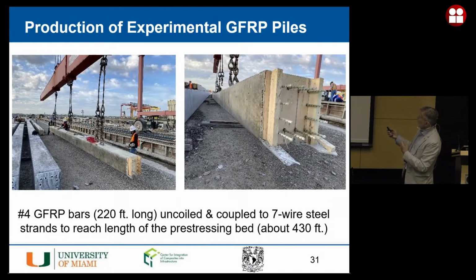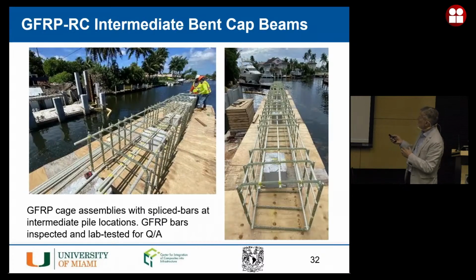So these are the piles that are picked up. These are 18 by 18 inches, so they have to be the same size of the piles using carbon FRP, but again, we had quite some time in playing with them. So the items that you see sticking out are the bars that we pre-stressed, but then inside the pile, there is also a cage of unstressed reinforcement. So those were number 8 bars, so 25 millimeters in diameter. And this is another picture. This is the cap. So you can see it's a conventional construction, nothing different.